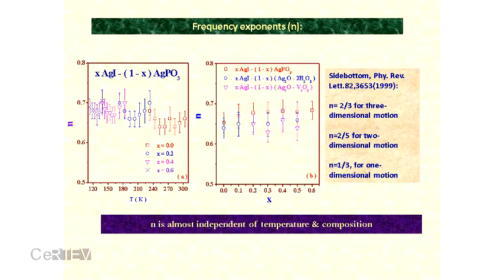Here we have shown you the frequency exponent. Here you can see the frequency exponent is almost independent of temperature and near about 2/3 for these glass systems. And so far, we have also plotted for several other glass systems also. There is little deviation from one system to another. And what does the exponent tell us?